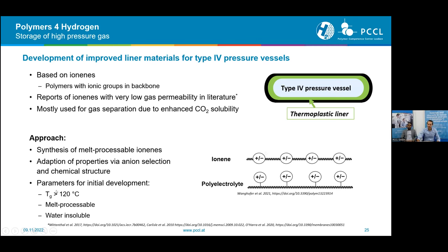For the initial development, we chose some parameters that we can measure fast. The first one is that the glass transition temperature needs to be above 120 degrees Celsius for an amorphous polymer. In case of a crystalline polymer, it would apply to the melting temperature then. That's mainly because this liner also acts as the mandrel for the filament winding of the pressure vessels, and it needs to be, of course, dimensionally stable during the curing of the composite overwrap.